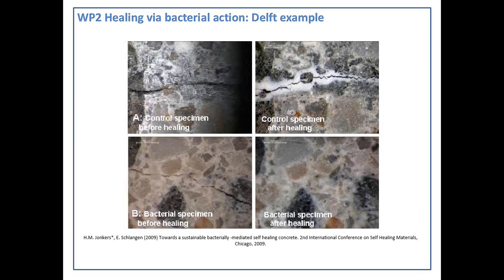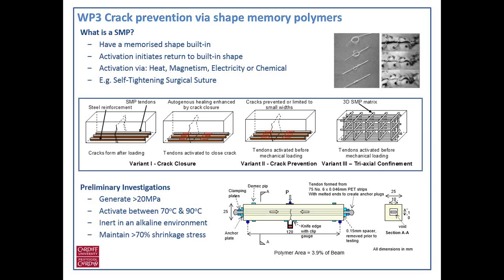I mentioned Bath were also leading on from what they were doing, and the point of this is to show that the limitations of natural healing can be overcome by introducing bacteria into the specimen. However, this still has its own limitations. So this works over a period of time, and it has a limitation to the size of the crack that it can heal. So the idea is to then combine this with the other systems to create a much more resilient self-healing system.